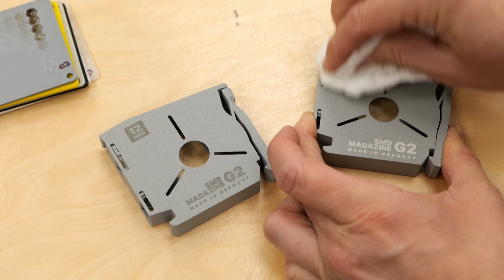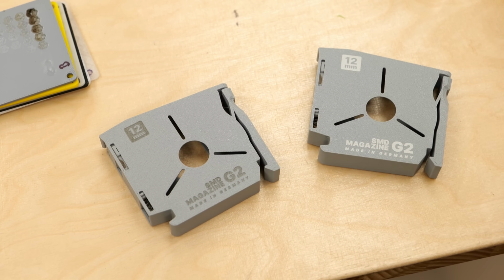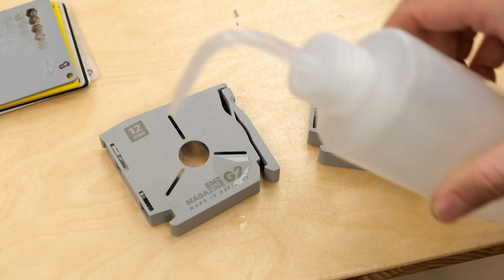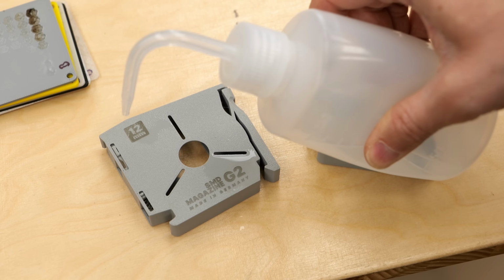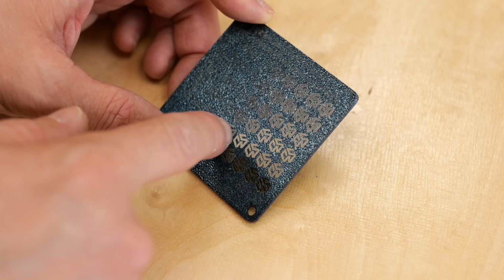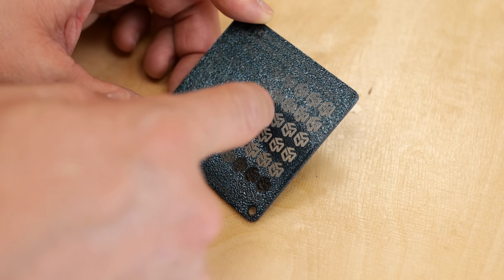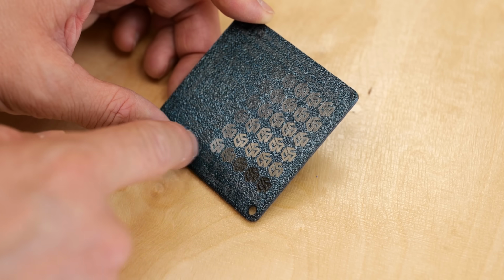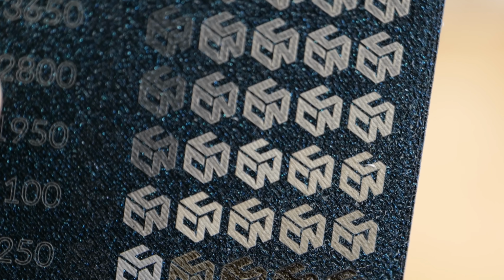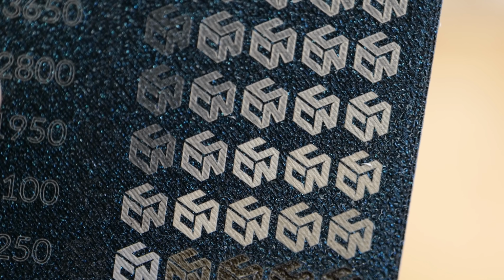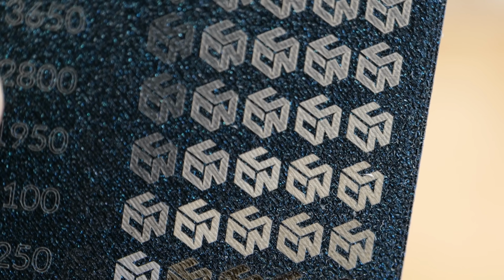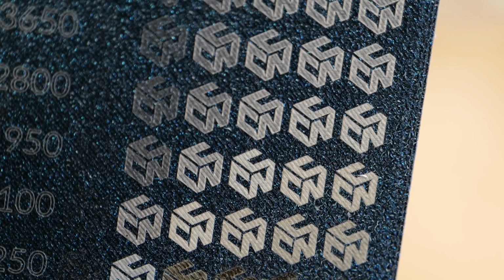I cleaned some of the samples with isopropyl alcohol, and the only thing I was really able to remove was a bit of smoke and soot that had stuck to the surface. The actual marking stayed very durable. Even scratching did not remove much of the contrast, though you sometimes see some scratches. That was a very encouraging result, because that suggests that the marking is not just simply sitting on the surface. It is actually a change in or near the material surface itself.